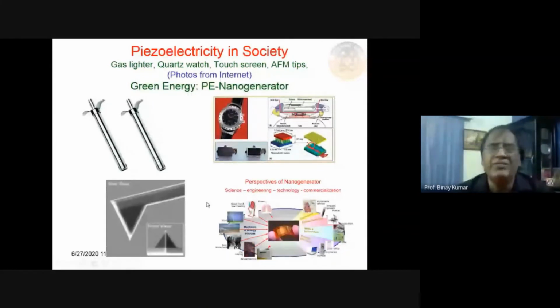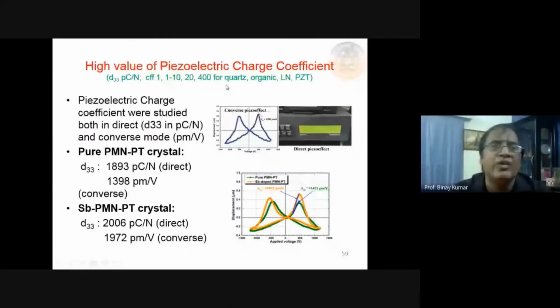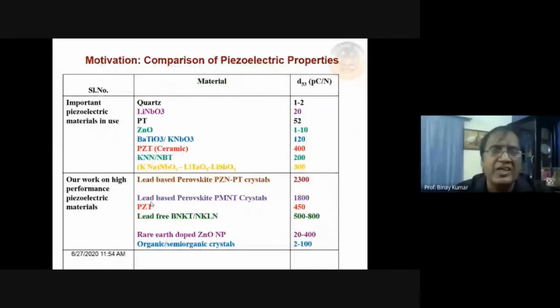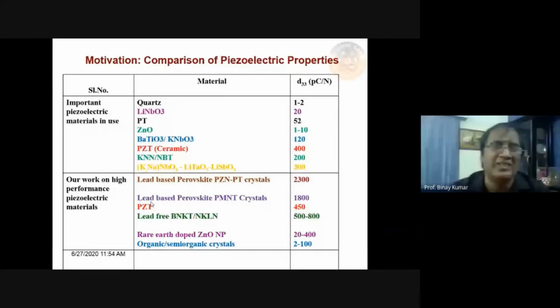So we have grown many crystals which have very high d33. Normally for quartz it is 1 or 2. For PZT, which is a very important material, it is hardly 400. We have grown many PMN-PT crystals in which this value is over 2000. So we are growing crystals and using them for piezoelectric applications. Now come to the application part quickly.